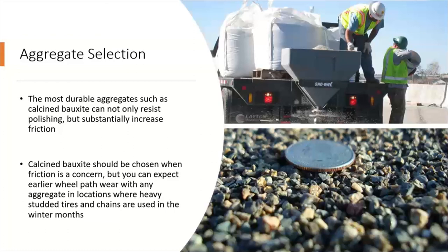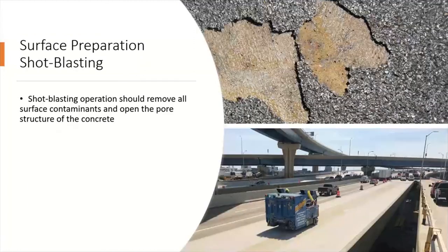Thin polymer overlays work great, and they work really well even if you do have some studded snow tire traffic and chain traffic, but they don't work forever. Shot blasting, that top left photo is the perfect example of a number of things that went wrong. There's white curing compound. This was a new bridge deck. We noticed white curing compound was not shot blasted off that deck. You should shot blast that white curing compound off the deck. If that doesn't happen, then it's just going downhill from there.